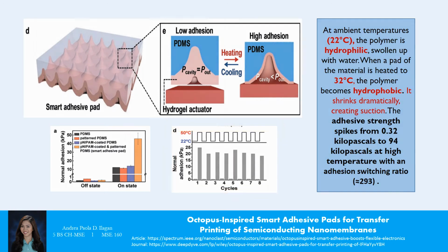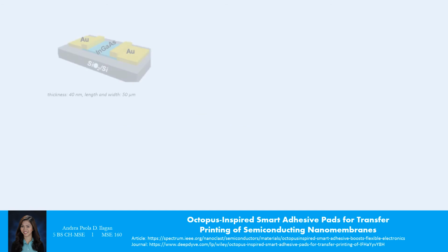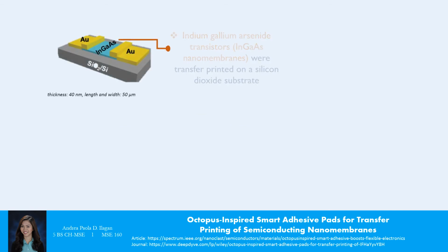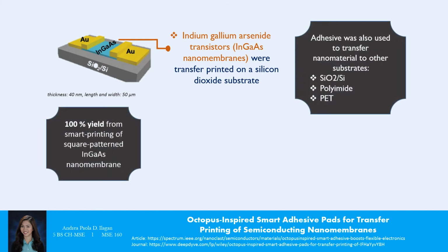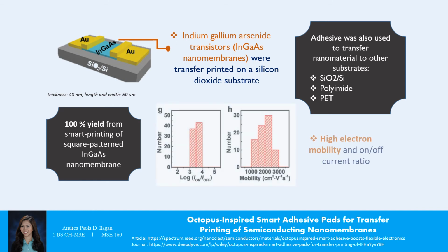To prove the concept, they transfer printed indium gallium arsenide nanomembranes on a silicon dioxide substrate. As a result, they were able to transfer 100% of the material without causing surface damage, not only on the silicon dioxide substrate, but also on heterogeneous surfaces such as polyimide and PET. More importantly, the transistor was working excellently with high electron mobility and high on or off current ratio.